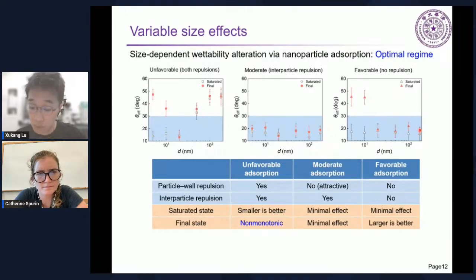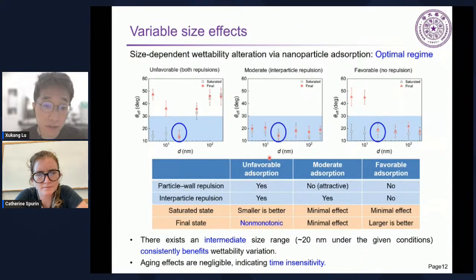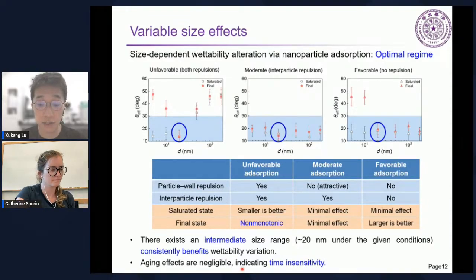Even more importantly, if we summarize all these results together, we will find an intermediate size range that consistently benefits wettability variation. And this is something exciting for applications, because if we can identify and predict this optimal range, then people can use it in a relatively safe way, and they don't have to consider too many complex factors. Also, we have evaluated the aging effects. So basically, the results are relatively general without time sensitivity.